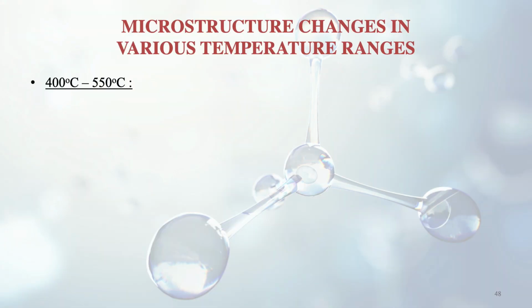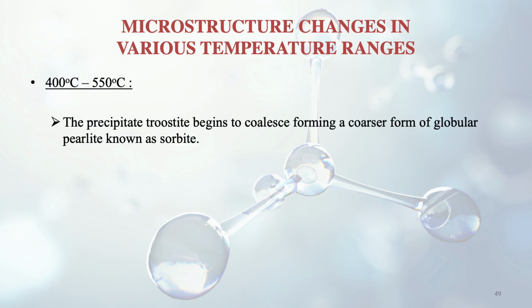Further, now we move on to a higher temperature, 400 to 550 degrees centigrade. Here what happens is that the troostite which was formed in the earlier range begins to coalesce, forming a coarse form of globular pearlite known as sorbite. So the earlier one was troostite, now it is coalescing and forming something coarser. It is not that fine, meaning the interstitial spaces are more now, and grain growth is taking place more rapidly instead of nucleation, and this is known as sorbite.